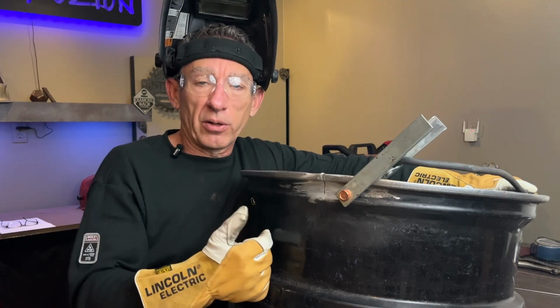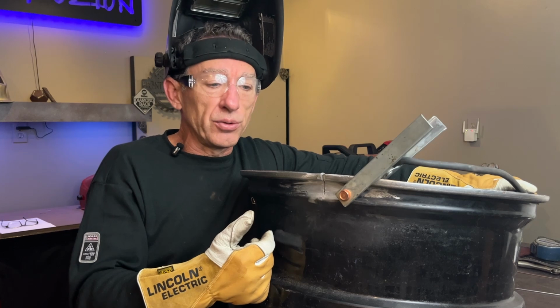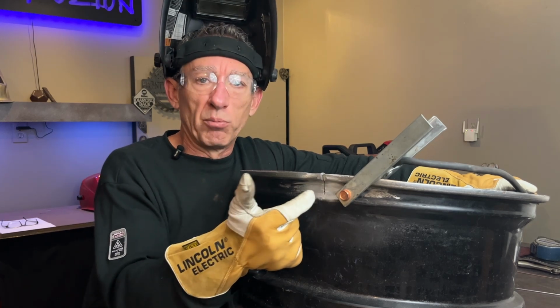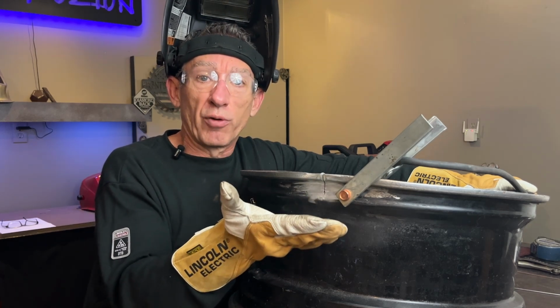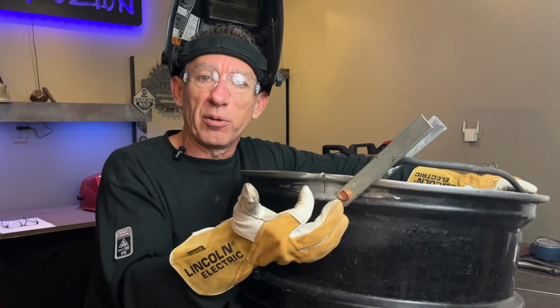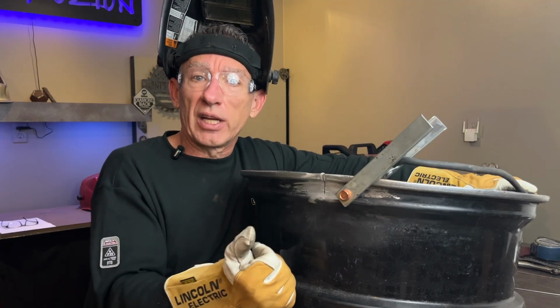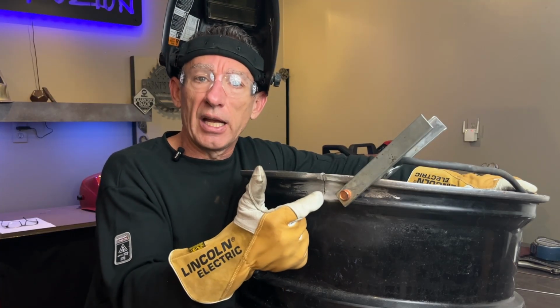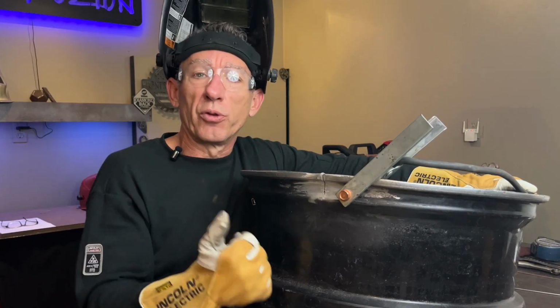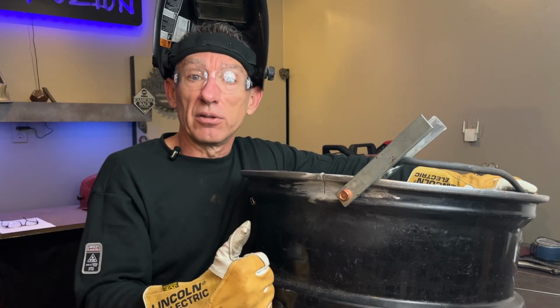One, it's going to let me get a better camera angle, I think. And two, I'm going to be putting more heat into the material as I go vertical up, and that heat's going to rise ahead of me and preheat that aluminum as I get to it, so I can be sure to penetrate in and overlap with the weld that I put in from the other side. Let's take a look and see if it works.